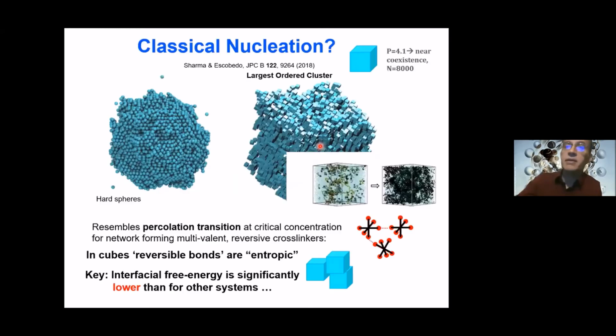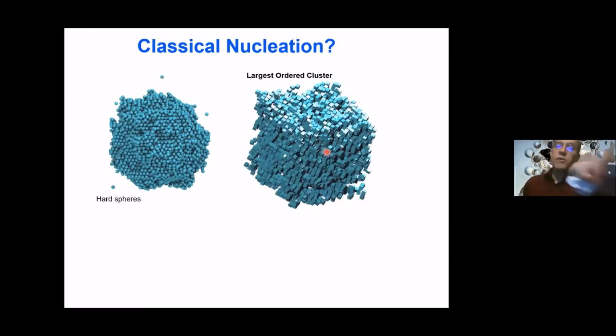Yeah, so in some ways, that's the idea. What we are saying is that when there is a full contact between the facets of two particles, that corresponds to basically chi. So this contact energy, when there is full contact, that's epsilon, which by a rough mapping corresponds to the chi parameter. It's a coarse-grained representation. You can make it more refined, and we also have some models to describe this in a more refined manner. But this allows us a quick mapping of these phase diagrams to test whether some of these ideas we had about optimizing compounds were on the right track. But for sure, those approximations can be made more rigorous.